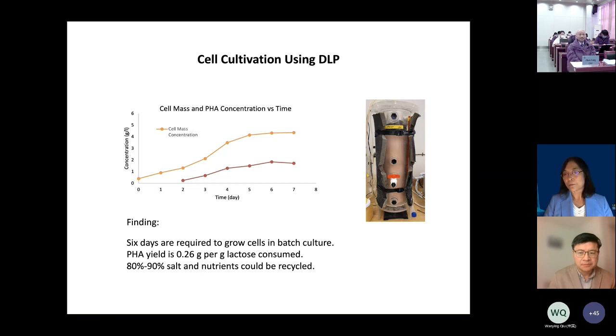That also is important. We're able to maintain pure culture, and so now we harvest the cells. Now we lyse the cells and extract the PHA. PHA has a high purity, and we have done some GC analysis with the HB and HV. We don't have to do extra or additional purification. So it's pretty clean, pure in that regard. Very good. Thank you for sharing those interesting results.